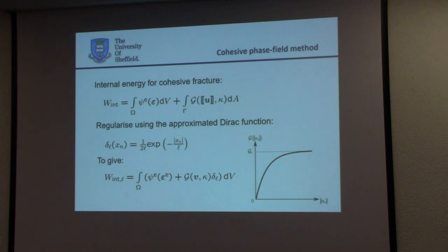When we define the equivalent for a cohesive zone, this term is the same, of course, but here we have a fracture energy function which is a function of the crack opening or the crack sliding, and a history parameter which is the largest value of the crack opening which has occurred. So this is essentially the difference then.